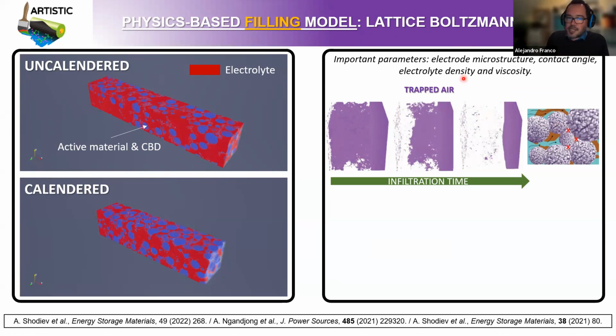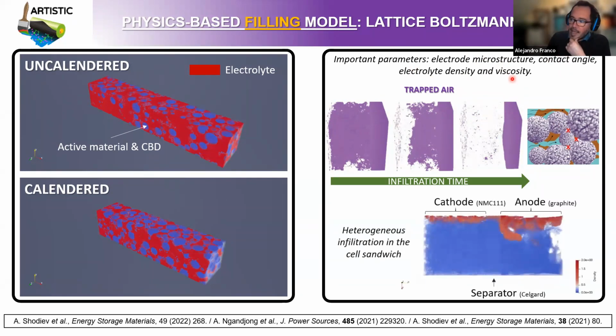This phenomenon is strongly dependent on the electrode microstructure, as we saw here, but also is strongly dependent on the contact angle between the liquid electrolyte and the electrode. It's also dependent on the electrolyte density and the electrolyte viscosity. And these properties can be controlled by playing with the chemistry, the chemical composition of the electrolyte. Okay. Here you see a result of simulation showing how heterogeneous the infiltration by liquid electrolyte of a cell sandwich can be. This is a simulation also in 3D, but here I'm showing a side view. In the anode, you have a graphite-based electrode.